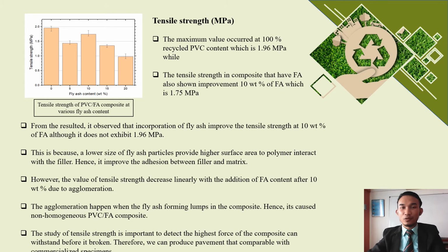This is because a lower fly ash particle size provides high surface area for the polymer to interact with the filler. Hence, it improved the adhesion between filler and matrix. However, the value of the tensile strength decreased linearly with the addition of fly ash content after 10 weight percentage due to agglomeration. The agglomeration happens when the fly ash forms lumps in the composite and causes a non-homogeneous PVC fly ash composite. The study of the tensile strength is important to detect the highest force the composite can withstand before it breaks. Therefore, the value can be used as a reference to produce pavement that is comparable with the commercialized product.